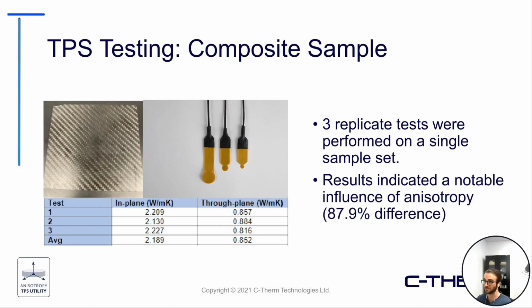Here we're showing another test set on some composite materials, again tested with the TPS method. Again, in this example, we can see about an 88% difference between the in-plane and through-plane thermal performance. So again, depending on the type of material that you're working with, if you were assuming that the average value here was representative of the bulk, you can really be biasing yourself and setting yourself up for failure, when in fact you can have some very large differences in thermal performance in these different directions within a singular material.